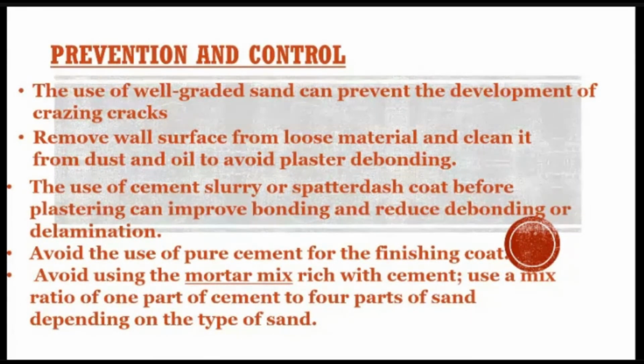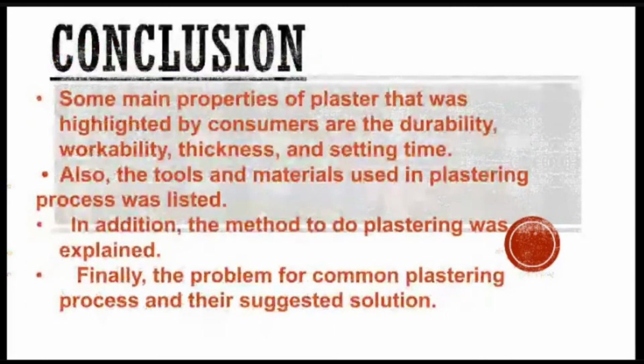Avoid the use of pure cement for the finishing coat. Avoid using a mortar mix which is rich in cement. Use a mix ratio of 1 part of cement to 4 parts of sand, depending on the type of sand.